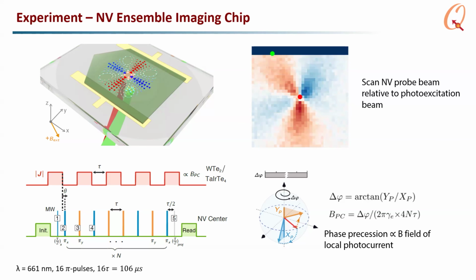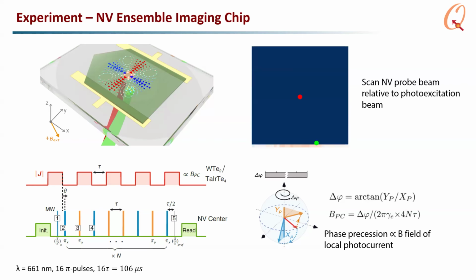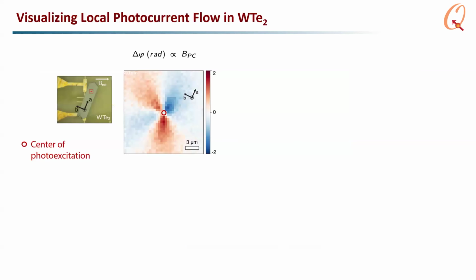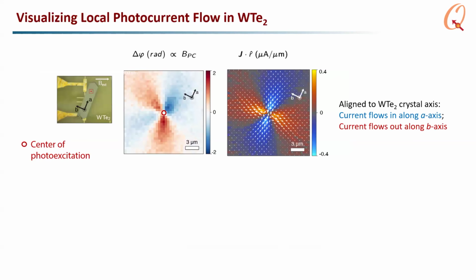Okay, so actually I see this very surprising pattern that switches sign 4 times. So what does that look like? If I invert the Biot-Savart law, I can get the current flow. And you can convince yourself that it has to be 4 vortices, where blue is just currents flowing in towards the center of the photoexcitation, and red is flowing out. So what we see is that the photocurrent flows out along the B-axis and in along the A-axis.